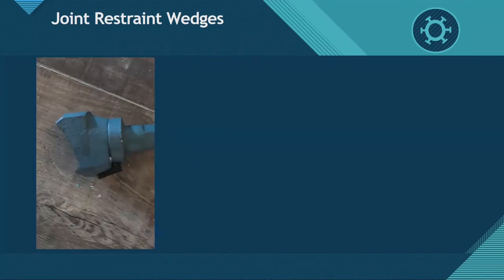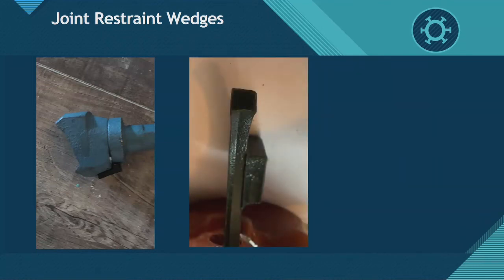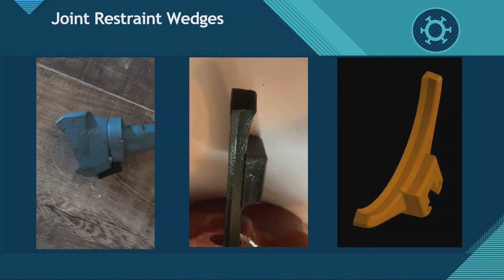So wedges for ductile, small, aggressive. Wedges for PVC, a lot longer, cover most of the circumference of the pipe, not all that aggressive of a tooth. And then one that's used for both PVC and ductile is going to be long, as I said, like the PVC, but aggressive tooth, so it bites into that ductile when needed to.